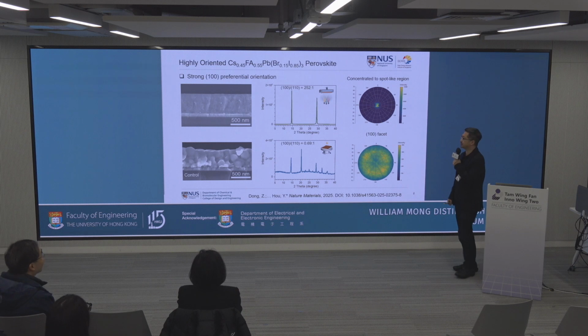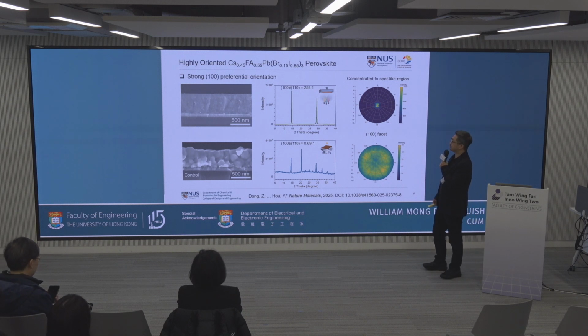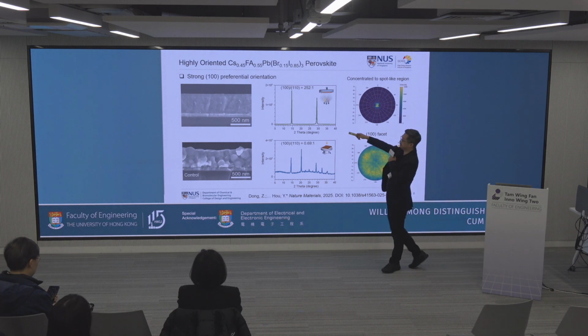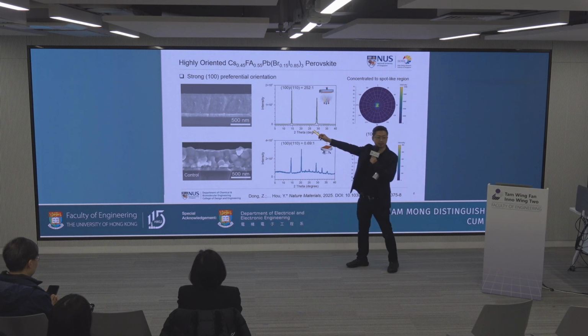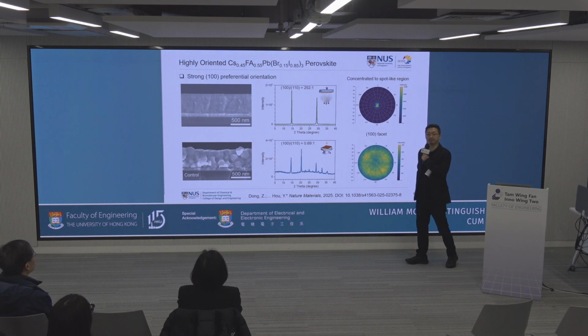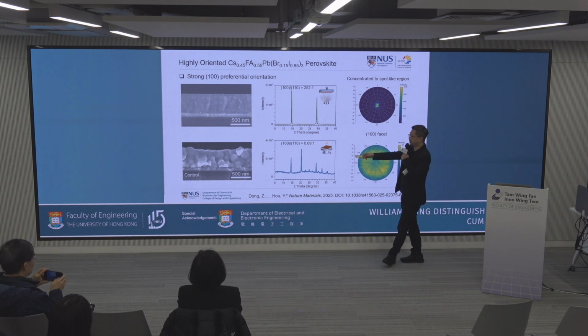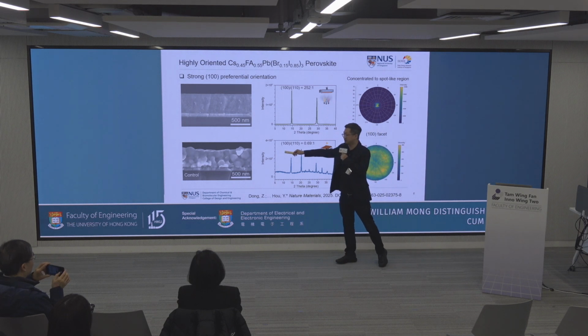Quite recently, we developed this evaporated perovskite solar cell. As you can see, by evaporation, the perovskite film is very, very smooth, like a mirror. And normally, if we deposit perovskite using solution processing, you can see something like this.